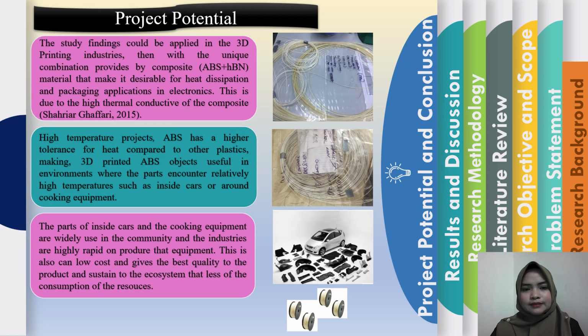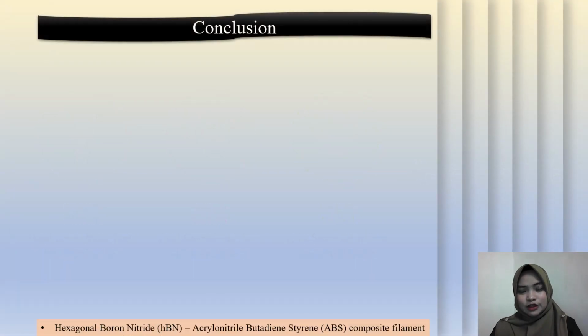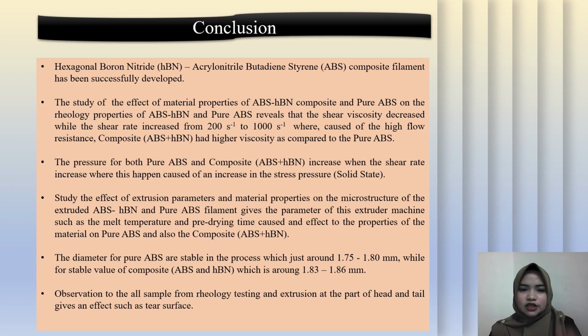And then we come to the conclusions. Hexagonal boron nitride (HBN) and ABS composite filament has been successfully developed. The study of the effect of material properties of ABS HBN composite and pure ABS on rheological properties reveals that the shear viscosity decreased while the shear rate increased from 200 to 1000, because in my study I started at a shear rate of about 200 and went up to 1000.